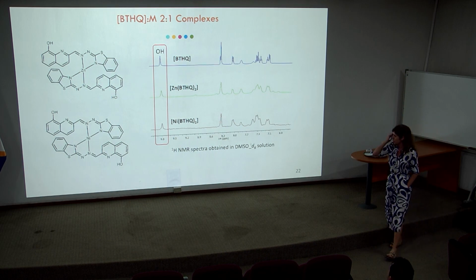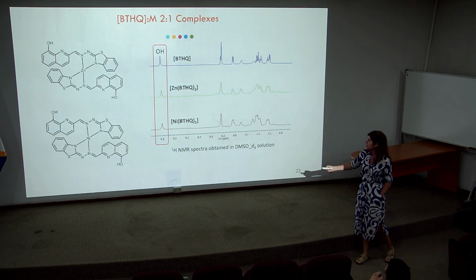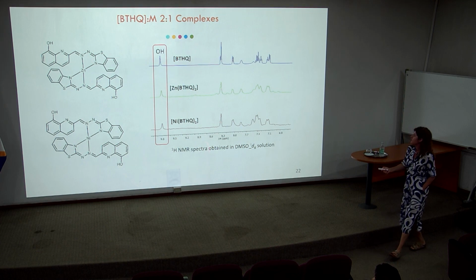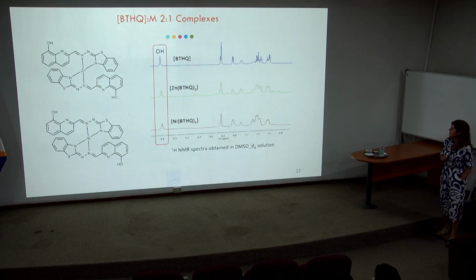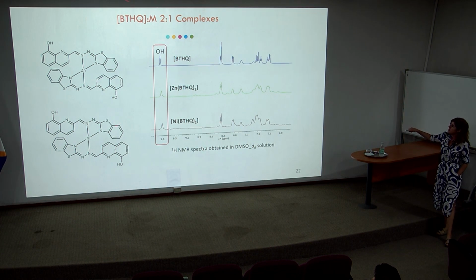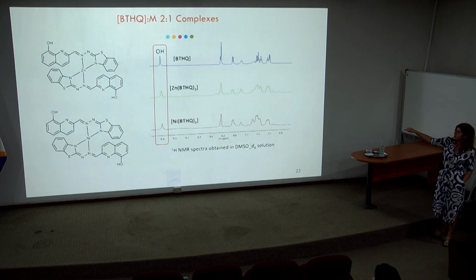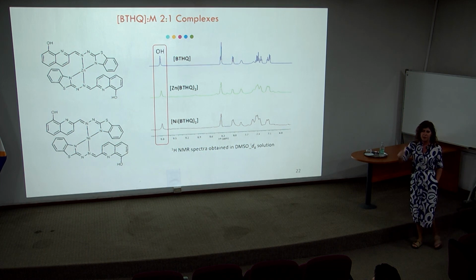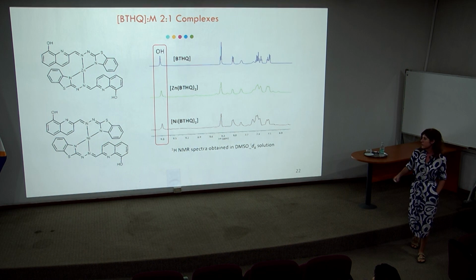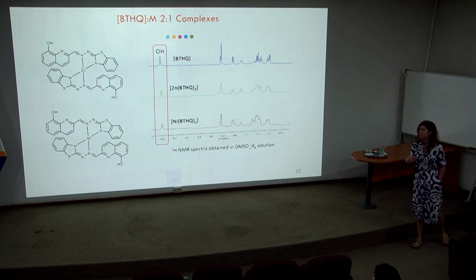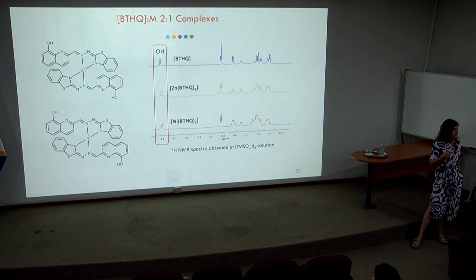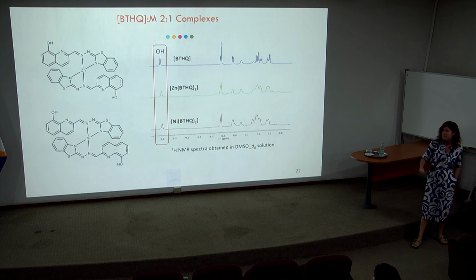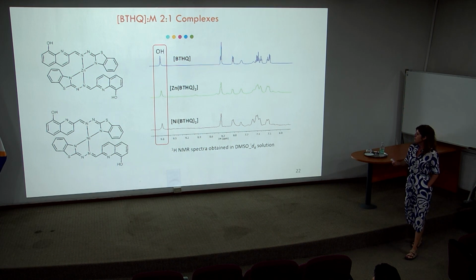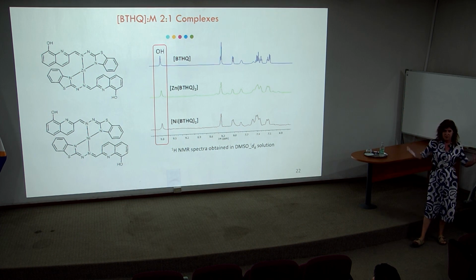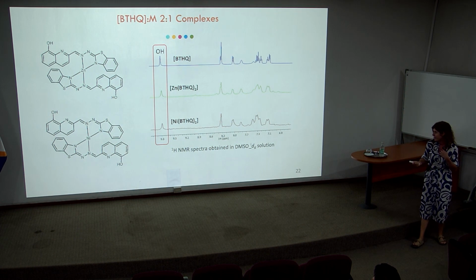And here I show you the spectra for the zinc and nickel complexes, the 1H proton NMR spectra in DMSO. And we can see that the quinoline moiety does not bind the metal ion in these complexes. So this ligand seems to have a very versatile mode of coordination towards different metal ions, because different ratios and different metals bind this ligand through different binding sites.